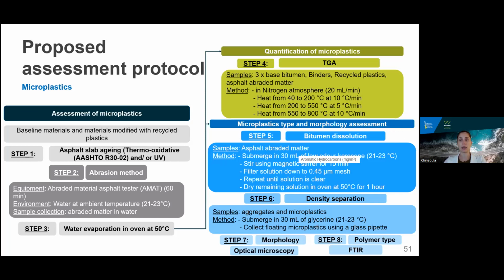The abrasion duration can be tailored to the amount of material required. However, we found a minimum of 1 hour to be suitable to remove a sufficient amount of material, and that was also creating a surface that was similar to that of an aged road.